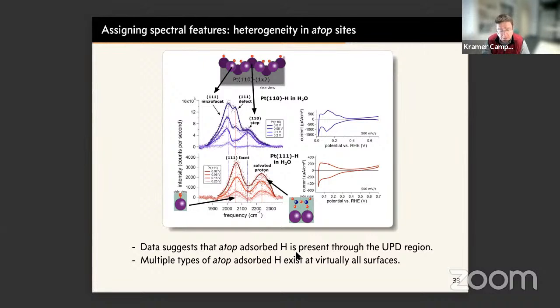Let's just say that partly in conjunction with theory and from some control experiments in comparison to UHV, you can assign these spectral features to particular populations of atop adsorbed hydrogen. We do so for the platinum 111 surface and argue that this lower frequency one is the 111 facet, that this higher frequency one, which is easily perturbed in the presence of salt, is a kind of solvated proton interfacial species, and that the more complicated spectrum on the 110 is the result of a 111 defect and this so-called 111 microfacet that exists on the crystallographically perfect 110 surface.